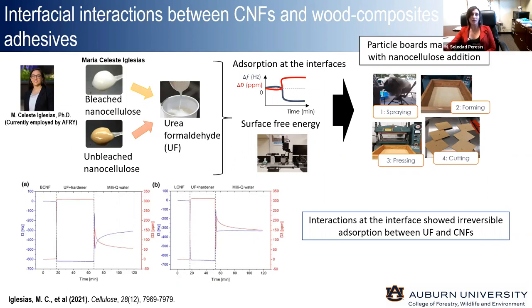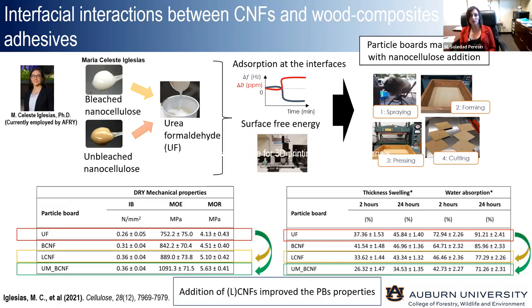And this translates what we saw later on when we produced the particle boards with a loading of the bleached and unbleached nanocellulose, which we also compared to commercially available bleached nanocellulose from the University of Maine. We saw a clear improvement on the mechanical properties based on internal bond, MOE, MOR, as well as the thickness swelling and water absorption in the case of lignin containing nanocellulose, meaning that our indication from the two-dimensional studies using QCMD were quite accurate, and we are further investigating this approach as a possible way of anticipating the behavior of our nanocellulose materials with other components as well.